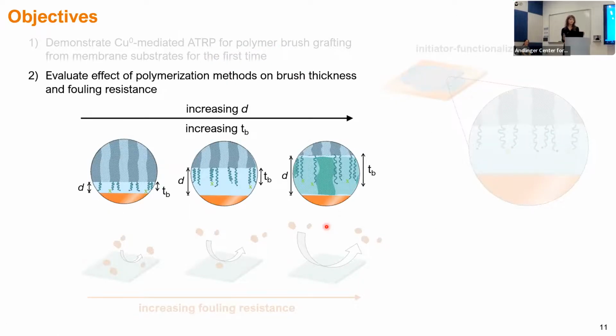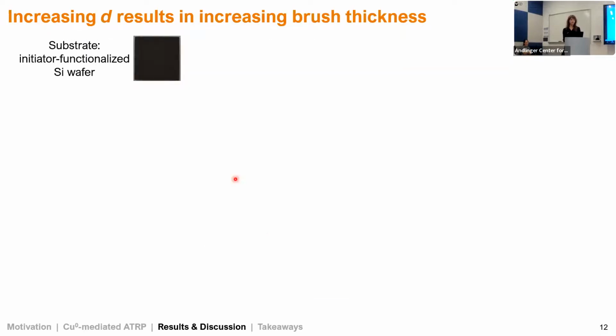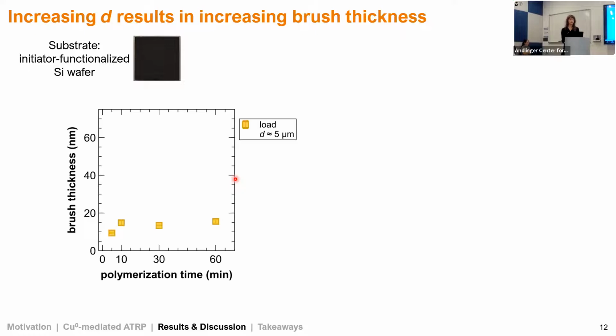So now we wanted to look at the effect of these polymerization methods on brush growth and fouling resistance, but I'll start here with brush growth. Okay, so now I'm going to show you results for brush thickness measured from initiator functionalized silicon wafers, which, as I mentioned, allows us to use ellipsometry for higher accuracy. And here we have brush thickness versus polymerization time, starting as always with the load method. We see an initial increase in brush thickness, and it's relatively stable after 10 minutes at about 16 nanometers.